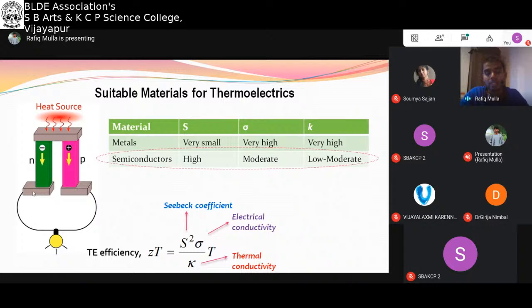In fact, people are working on different heat sink designs, again nanostructured heat sinks where the surface area is very high. If one can mount such heat sinks on the cold side, with water flowing on those sinks, because of the larger surface area they can effectively remove the heat from the cold side. But still it is not a commercially realized concept. So people are working to make better heat sinks so that a better temperature gradient is always maintained for a long duration. But presently in commercial devices, people use cold water flow along with a sink. So that is in fact working effectively.